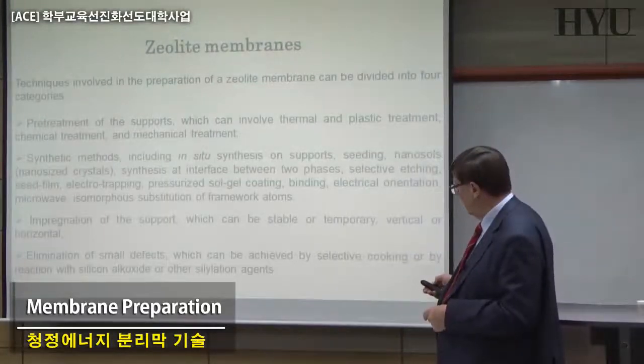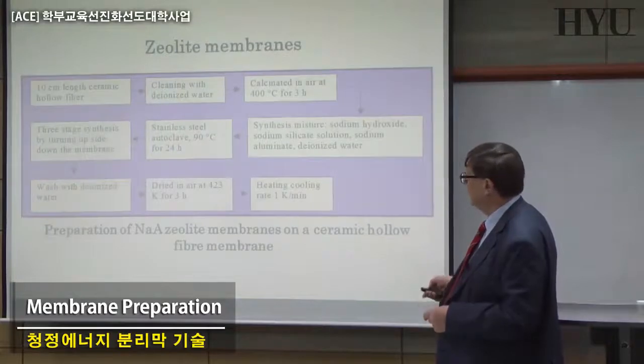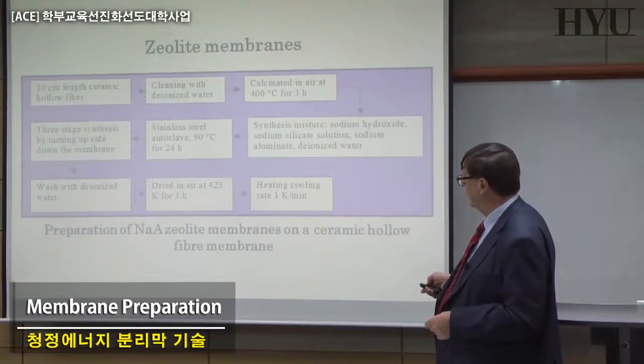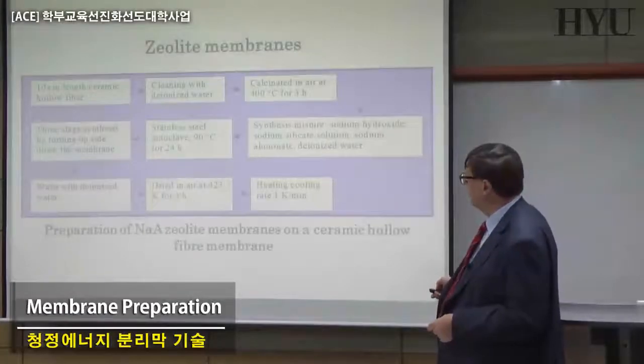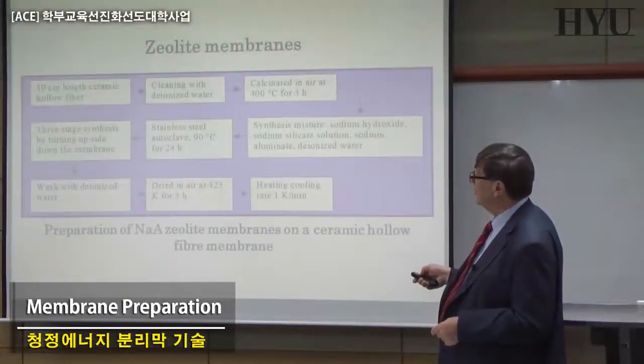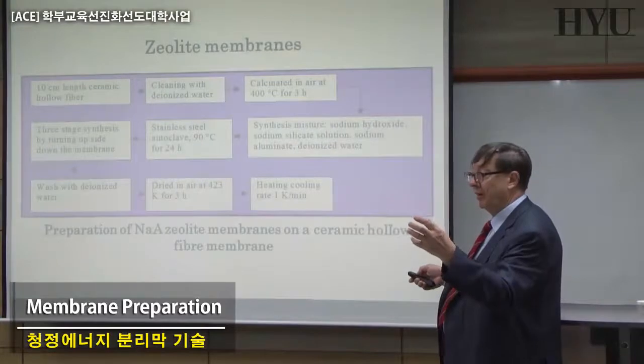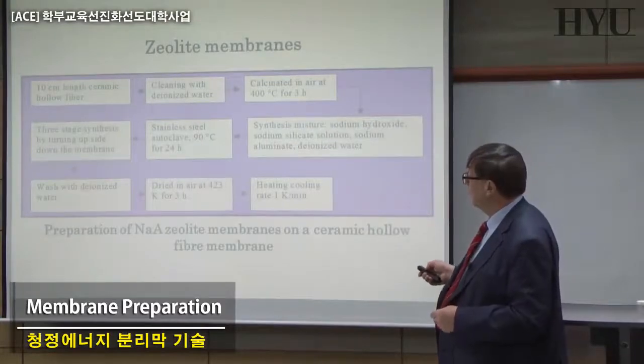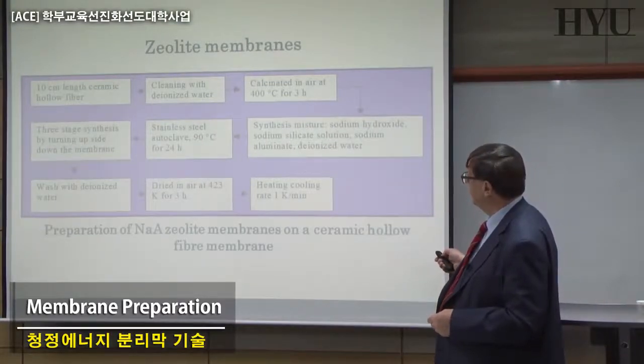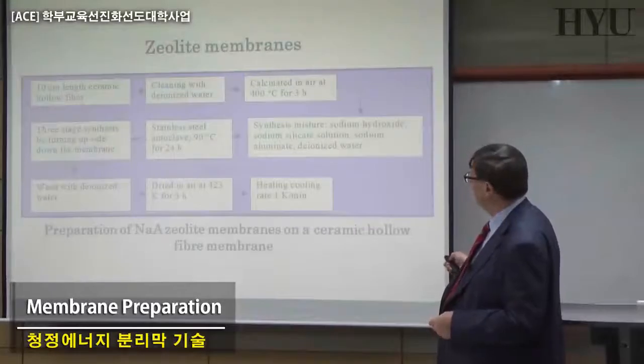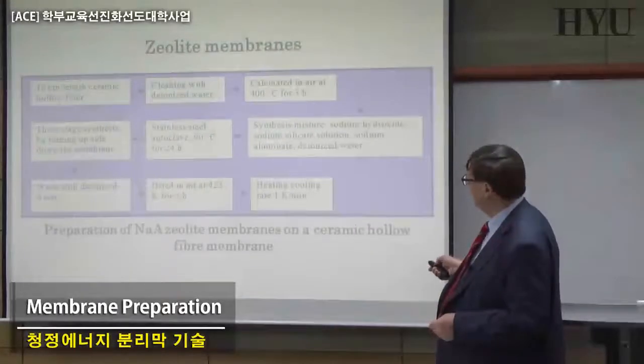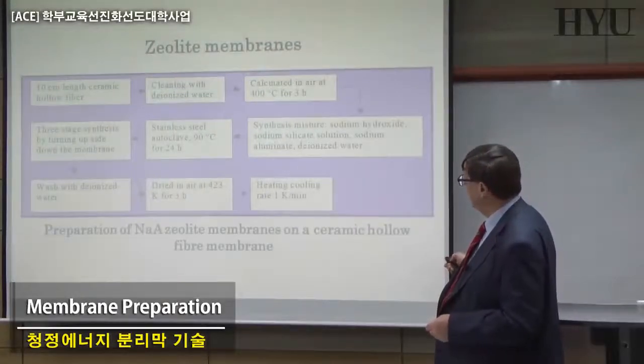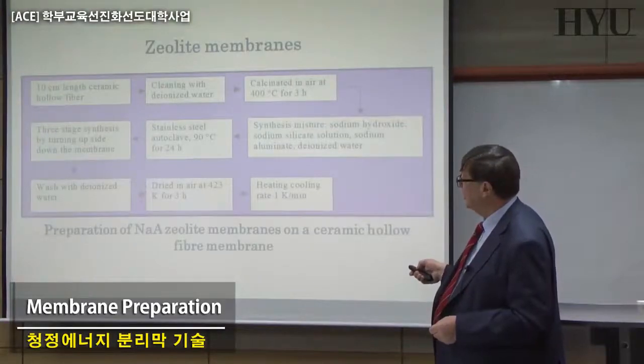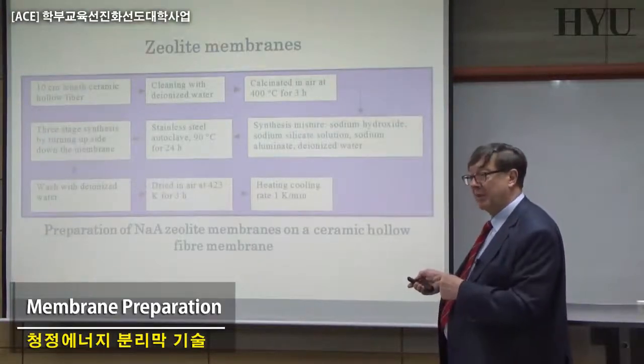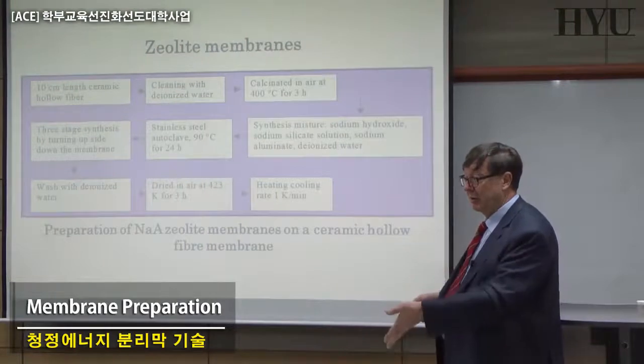This is done today, and at the end you can have, this is the procedure. This is one of the zeolites on the ceramic hollow fiber membrane that we are producing. And you can see here, you start by buying a ceramic tube, and you clean it, you calcinate it at a certain temperature. After that you prepare your mixture, with sodium hydroxide, silicate, sodium aluminate, water, and you just go into the autoclave. They are prepared, not just as in nature.